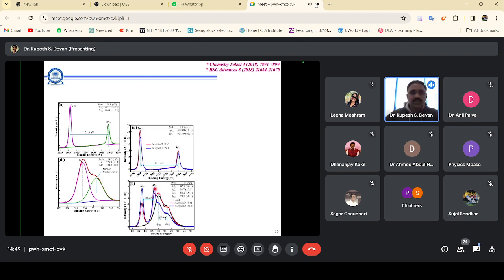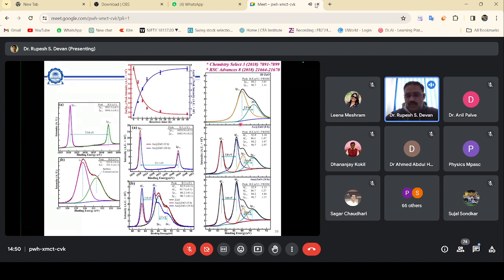For this purpose, we have used different reaction times. You can see here that initially zinc remains intact in its own stable format. And when you decorate with gold, as the gold layer on the zinc oxide increases, the zinc signal goes down, and obviously the gold signal comes up in XPS. Then you can realize that when you increase the reaction time, the decoration of gold reaches saturation at approximately 24 hours of reaction. That means after that, even if you put these zinc oxide rods in a gold solution, no more gold is going to decorate this particular structure. And gold, rather than getting oxidized, remains in its metallic form.